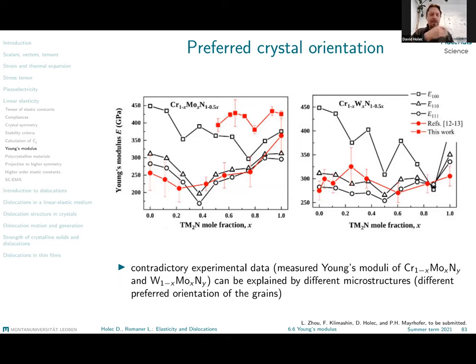the resulting indentation modulus, which relates the deformation, the depth of the indentation with the force acting on the indenter, we can relate it with the directional Young's modulus. And here we show a clear example of this directional dependence. These red data points are